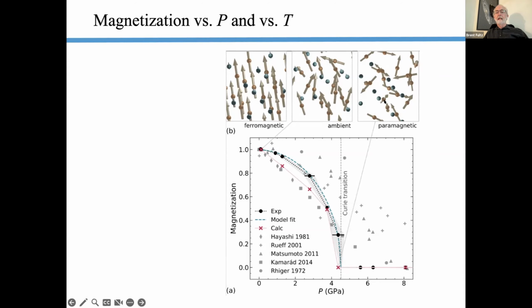The paramagnetic state, as you expect, would be more random. And this is the pressure dependence of the magnetization. Our points are here, the black ones. There's been some X-ray magnetic circular dichroism experiments. There's quite a number of measurements. The computational work is the red crosses here. This is when we gave them, it's kind of a closed loop though, because we kind of gave them magnetization information to try to figure this out. So it's not quite a fundamental principle, but it's interesting to look at this.